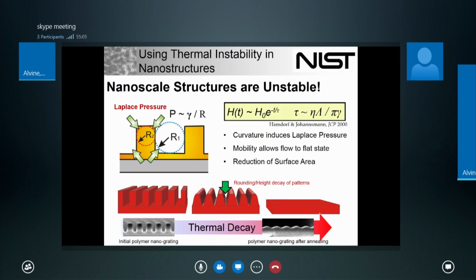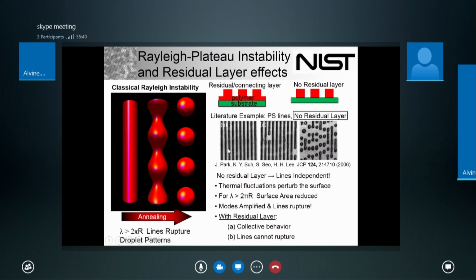And so the way you can do that is by looking at the thermal instability of the polymers. This is work that was done at NIST back when I was there about 8 years ago. There, we figured out that nanoscale structures are pretty much unstable because they have all this surface energy that wants to make them flat. You can see all of these little sharp corners want to go away, and the surface wants to essentially height decay into a flat substrate. And that's exactly what will happen if you let it go. When you take a polymeric surface and heat it near the glass transition point where it can flow, it'll go flat. What's more interesting, other than this slumping behavior, is if you look at threads.